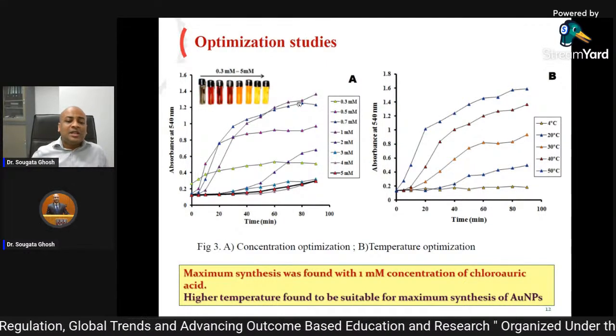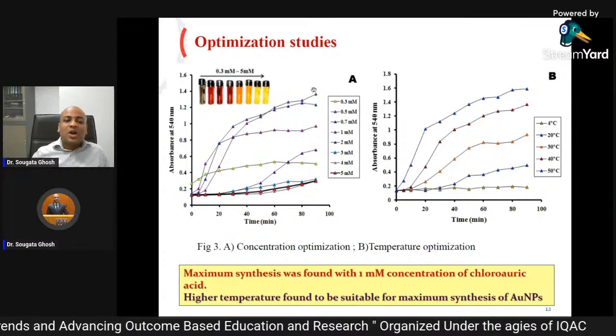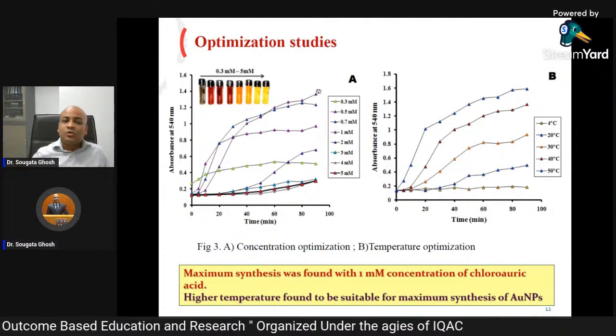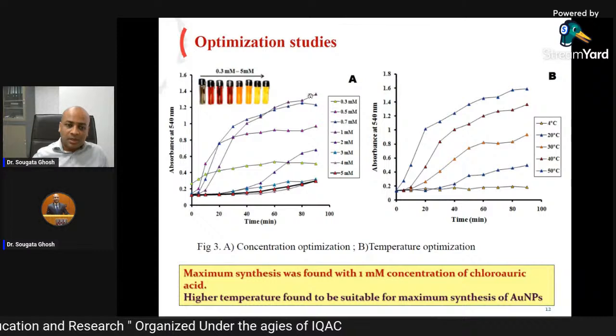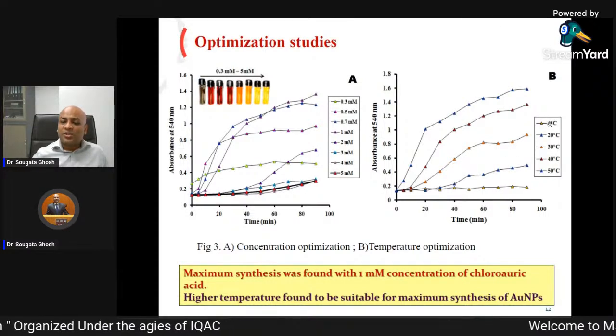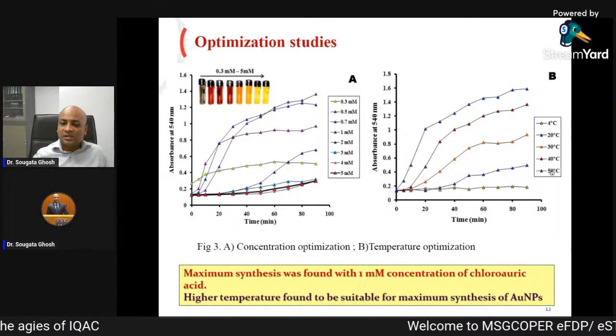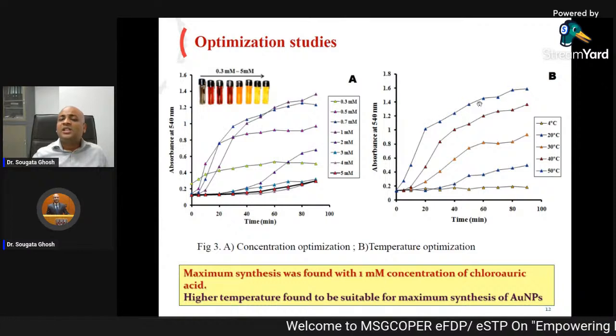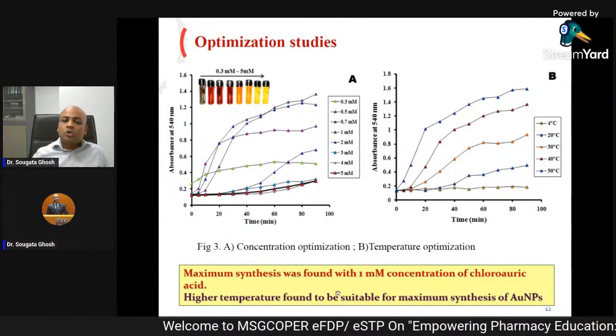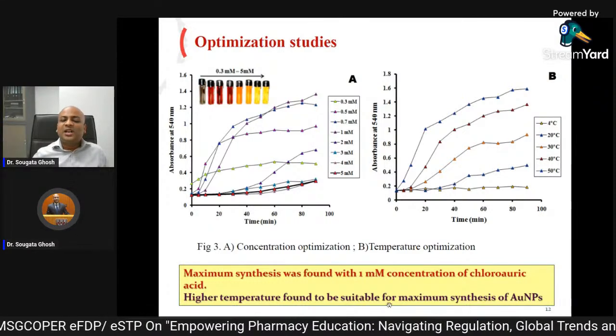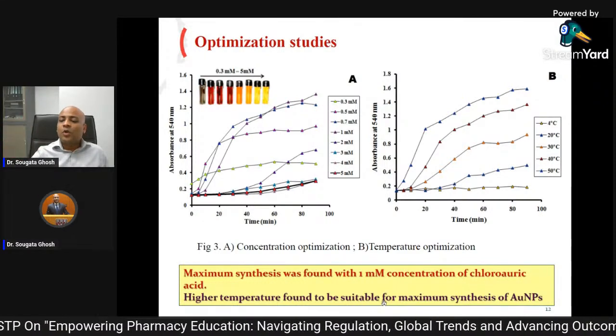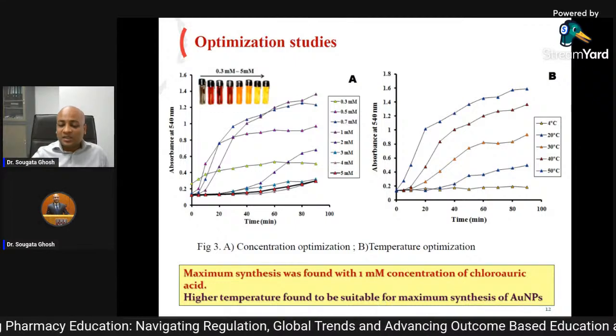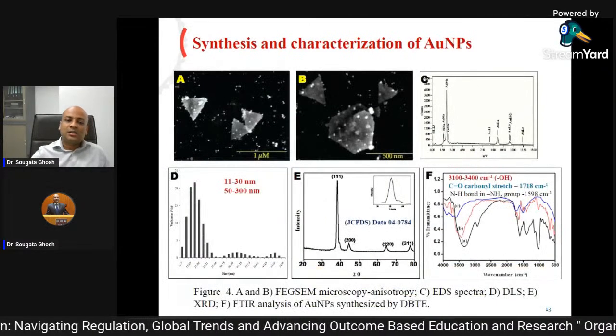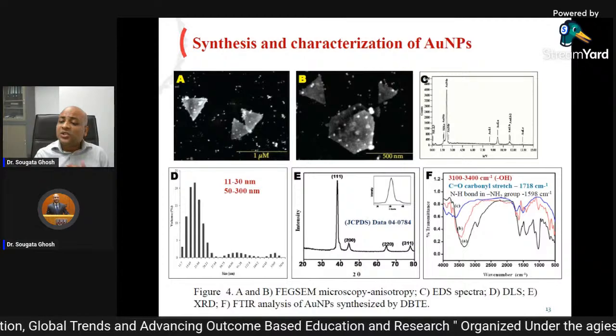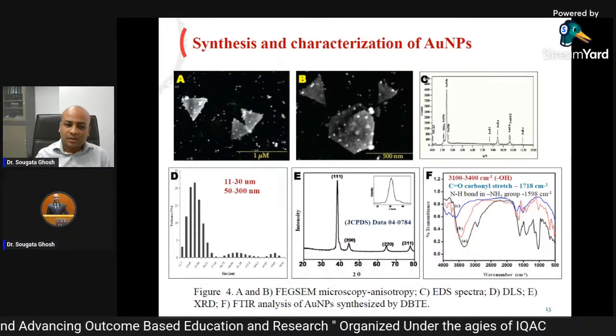So we found that 1 millimolar was best in synthesizing gold nanoparticle. It was highest. Similarly, we varied the temperature from 4 to 50 degrees Celsius, and we found 50 degrees Celsius was best. So 1 millimolar concentration of chloroauric acid and 50 degrees Celsius was most effective in synthesizing these gold nanoparticles.